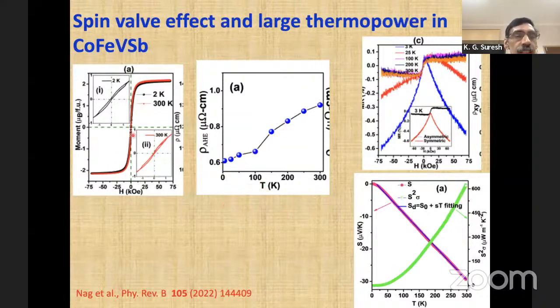Here, of course, you see that it has what is known as a double shifted hysteresis loop at low temperatures, 2 K. This is CoFeVSb. In fact, it's a puzzle even today for us. Whenever there is vanadium, things are going to be very, very interesting for whatever reason. It shows some kind of partial density of states, which is contributing to an anomalous behavior. Then you see what is like a spin valve behavior.